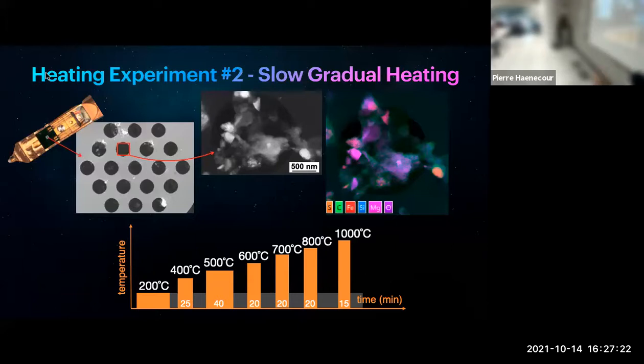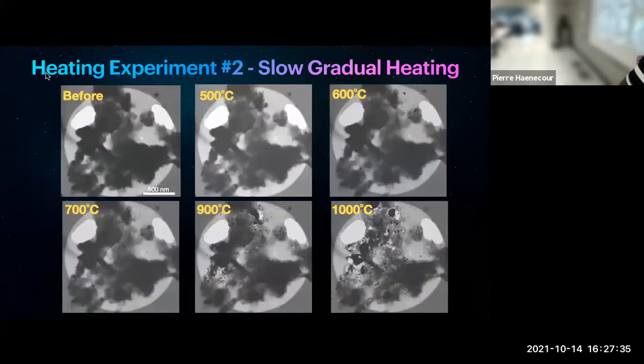In particular at 500 degrees, we tried to leave it longer to see if any changes happened over the long term that we didn't expect. We didn't see any additional changes as we left it at 500 degrees. If we compare the different steps, I'll show you all the bright field images as you go from room temperature to 500, 600, up to 1,000 degrees. It basically shows you the same trend.